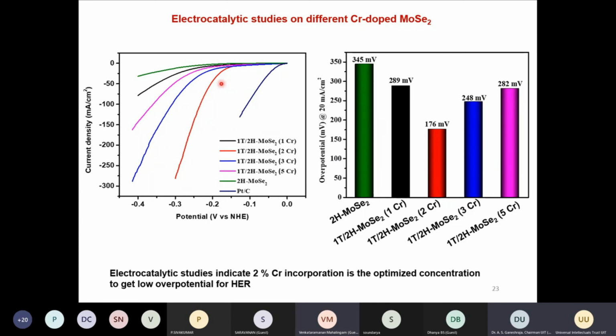But as you can see here, we have varied the chromium amount to see which one shows the best activity. What we found is that 2% doped chromium shows better activity compared to other samples. Upon increasing, of course, 1 shows slightly better, 3 shows slightly better, but later after 5, the activity decreases again. So 2% is the optimized concentration of chromium doping inside the MoSe2, which shows better activity.